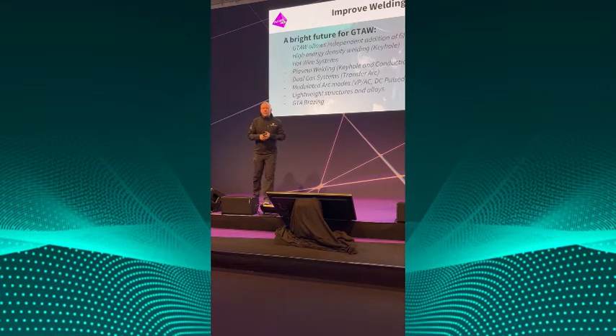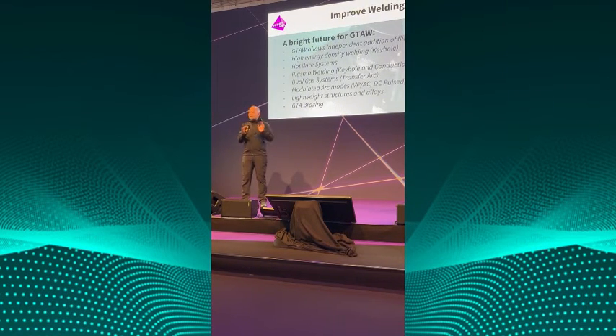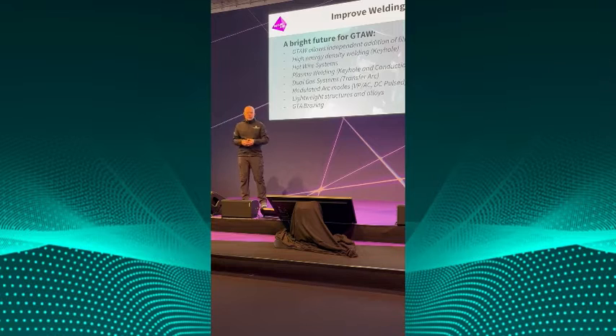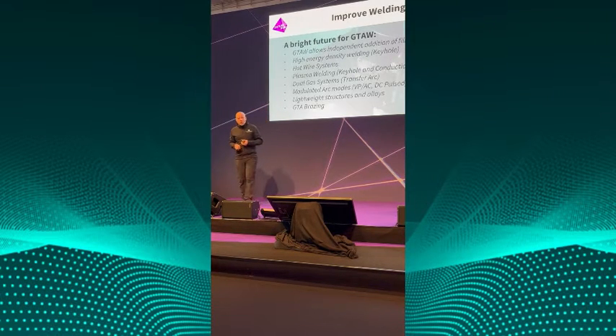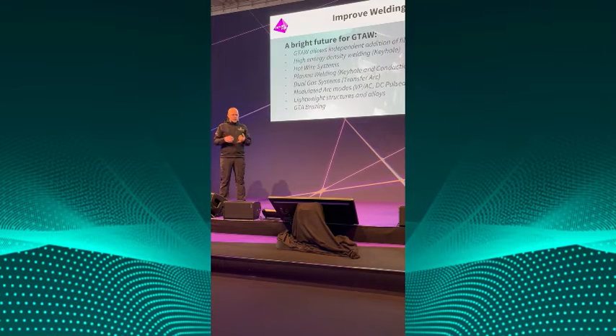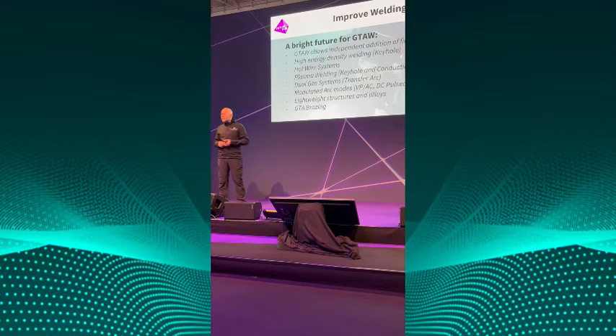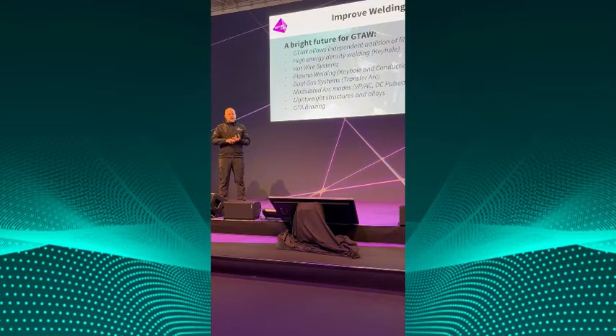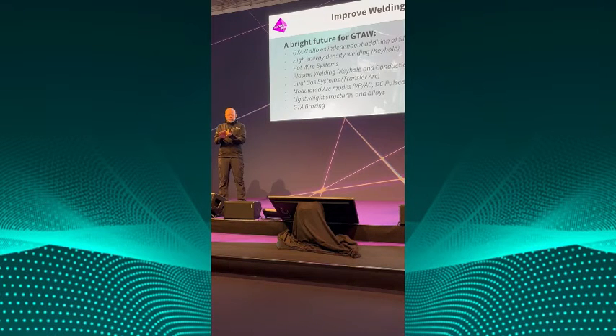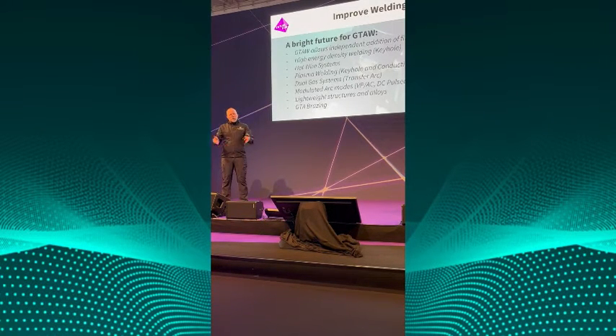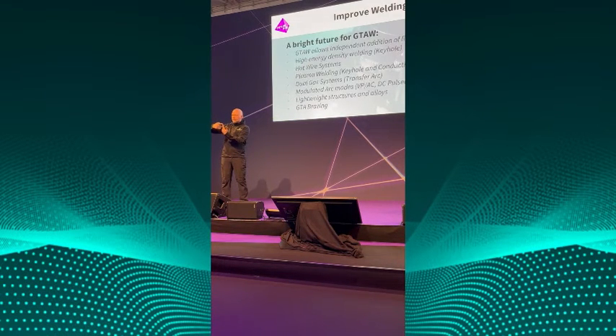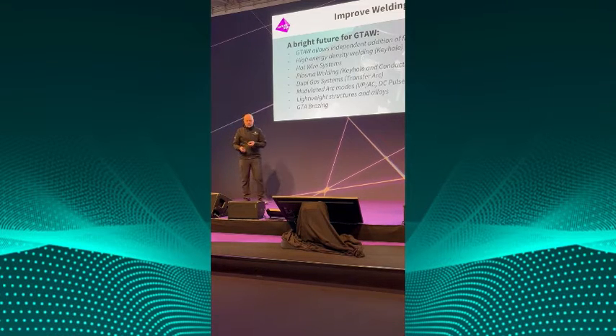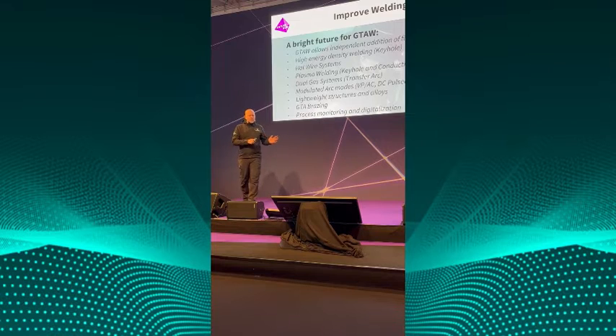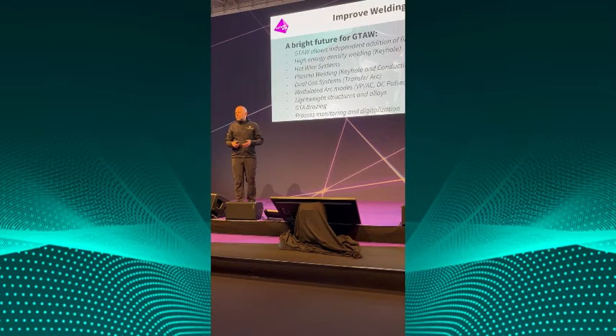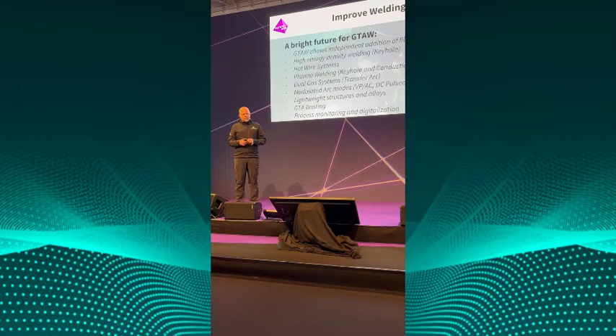We spoke about welding, but by definition, if the filler material is not the same type as the base material, it's called brazing. So gas tungsten arc brazing. Some know it as TIG brazing or silicon bronze filler wire. Fantastic possibility, so you don't melt the base material, so you can put materials together which usually don't belong together. Coming from Switzerland, like the cheese industry, you can have a copper bucket, but on the outside a stainless steel vessel. So at one point you need to fuse them together, and GTA brazing is the ideal process for that. And of course, since it's so stable, process monitoring and digitalization is the ideal starting point in TIG welding.